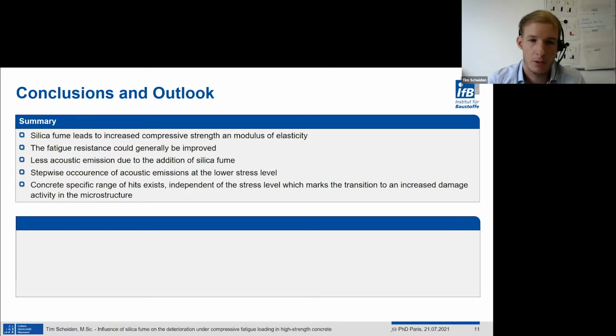Okay, so let's come to a short summary. We have seen that the addition of silica fume leads to an increased compressive strength and modulus of elasticity. The fatigue resistance could generally be improved, considering the number of cycles to failure. In addition, silica fume also leads to fewer acoustic emission hits under fatigue loading. Based on the acoustic emission, differences in the deterioration process between the stress levels could be shown, which becomes clear from the stepwise curves of the hits compared to the S-shaped curves. Furthermore, a concrete-specific range of hits could be detected up to where an increased damage activity in the microstructure occurs.